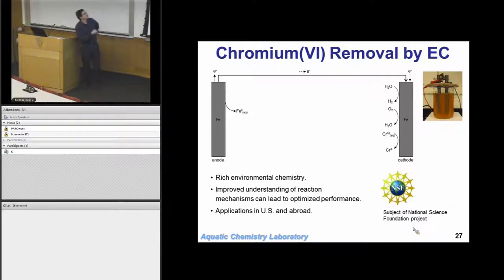So this is electrocoagulation. There's the iron anode releasing ferrous iron. That ferrous iron, that's iron in the plus 2 oxidation state. Rust is iron in the plus 3 oxidation state. That iron 2 is a good reductant to remove the chromium 6. So this stuff here, the Cr6, that's what we're trying to get rid of. That's the hexavalent chromium. But we can reduce it with the iron 2.